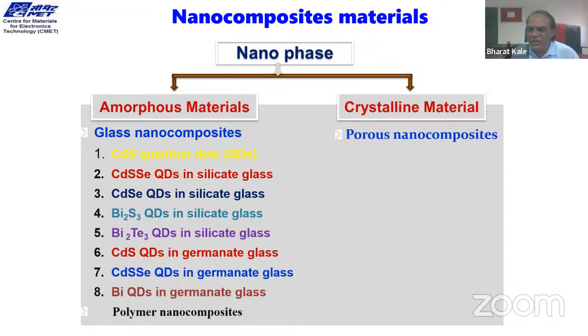and they are amorphous in nature. The 2.5 nanometer or 3 nanometer particles are very, very amorphous in nature. When you have cadmium sulfide as 5 nanometer, 10 nanometer, you see a very broad XRD, because amorphosity is much more in these materials. So what we thought is, glass is amorphous, so in this amorphous glass we can have